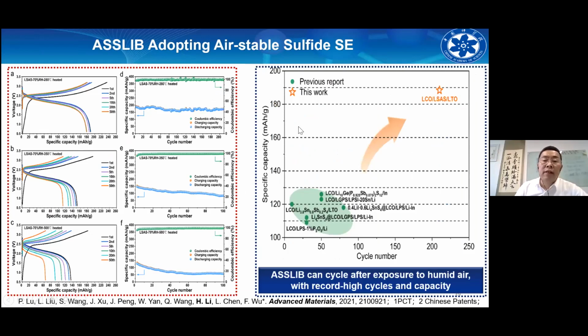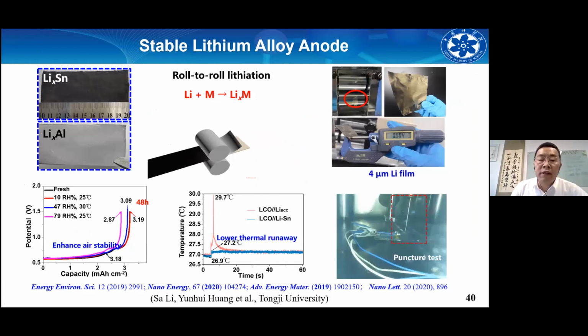And here is the summary of the batteries using this kind of air stable sulfide electrolyte to get the cycle life and high energy density. And for the anode side, there are a lot of possibilities. Today, I just showed lithium alloy, because this can be easily fabricated by roll-to-roll technology. The research group from Tongji University does this job, which is quite practical and can be scaled up.